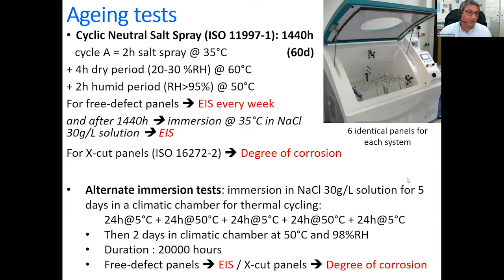So in the cabinet, we've got the free-defect panels, and EIS measurements were realized every week. But after this initial period in the salt spray cabinet, the panels were taken out of the cabinet, and then they were immersed in the sodium chloride solution at 35 degrees C. And then they were evaluated using EIS. This was done in order to see if the salt spray period could have an effect on the barrier effect for a further immersion test. Of course, we also have some X-cut panels that were evaluated using the degree of corrosion.